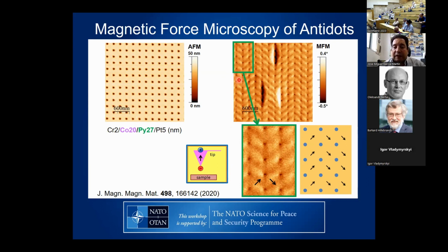You can see that in the magnetic contrast, there are some regions like this one, which exhibit a tiny contrast. If we focus our attention on this unit cell, you can see that we have a bright region here, and we have a dark region here. So we have a magnetic moment that is pointing like this. And it's doing the same all along this row of unit cells.